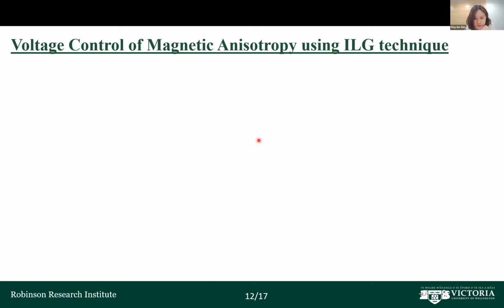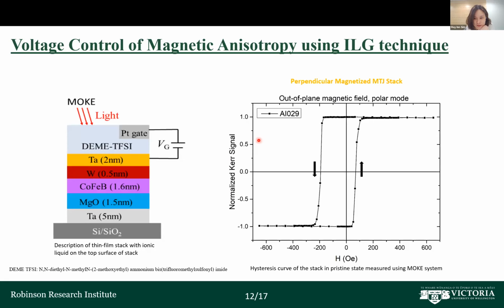I have one more question for you. The remagnetization from in-plane to out-of-plane sounds like the implementation of a two-dimensional system right now. Has it been possible to implement a truly three-dimensional spatial magnetic anisotropy distribution system? That's a really good question. This technique can be used to change only the theta direction from out of plane to in plane, but for the phi rotation within the x and y direction, we cannot use this technique.